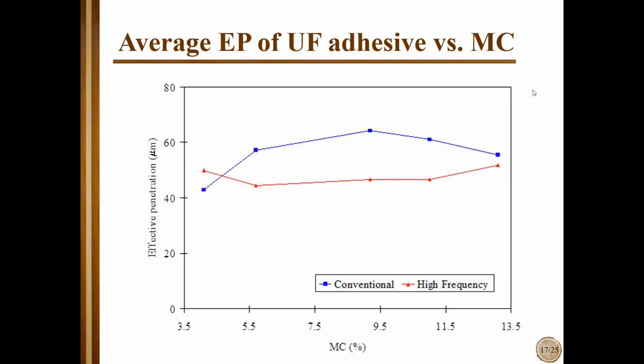And now I will show you some results on effective penetration of urea-formaldehyde adhesive versus moisture content. The blue line is conventional hot pressing, and the red line is high frequency heating. For high frequency heating, you can see that there are no significant differences in adhesive penetration with regard to moisture content. This was quite logical to explain, because when you use high frequency heating for curing, the adhesive starts to heat up immediately. And what is more important, the adhesive will heat up more intensively than wood.